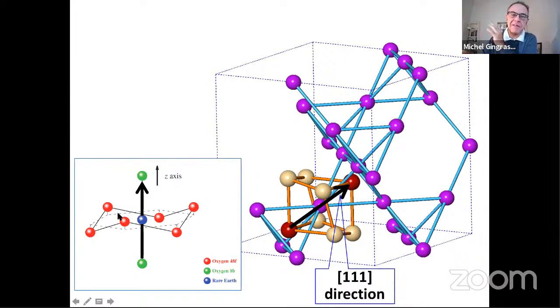You have a displacement, essentially, as if you took a regular cube with the oxygen and you squished it, but kept the volume constant. So these six oxygens get puckered, and perpendicular to this axis here you have an oxygen that is moved up, an oxygen that is moved down, and you have therefore an anisotropic environment around each of the rare earths. And this distortion is very large.